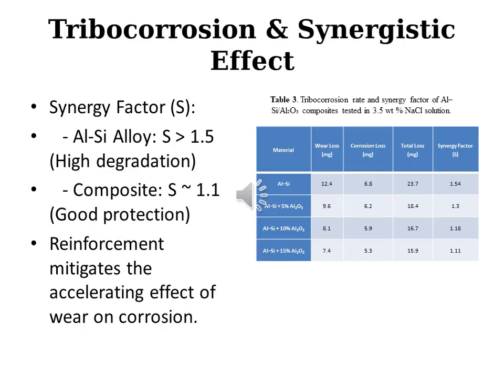In slide 8, tribocorrosion and synergistic effects. Now discussing the core of this study, tribocorrosion. We calculate the synergy factor S. For the unreinforced aluminum silicon alloy, S was greater than 1.5, indicating high degradation. However, for the composite, S dropped to approximately 1.1. This proves that the reinforcement effectively mitigates the accelerating effect that wear usually has on corrosion.